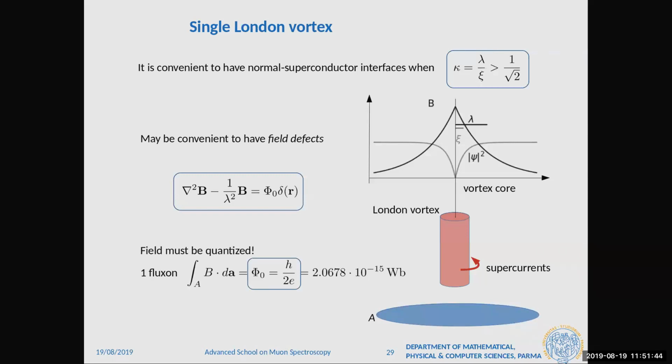And this testifies to the quantum nature of superconductivity. It really is one quantum, and the one quantum is h over 2e. This is really 2e in normal conventional superconductors, so it tells us that electrons go two by two there, in pairs. And if you simply add, you see this is B over a length scale squared, so exactly like that. So this is the equation we will have to think of.